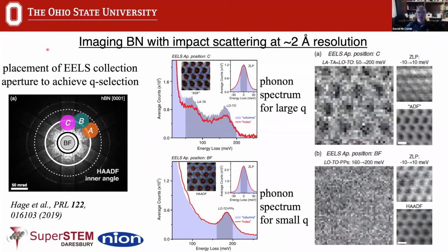And that's shown here where they're able to take EEL spectra that are acquired away from the zero order beam, so out here at a different position in K-space, and then that enables us to actually get spatially resolved phonon mapping. And you can see some of the structure in the hexagonal boron nitride here.